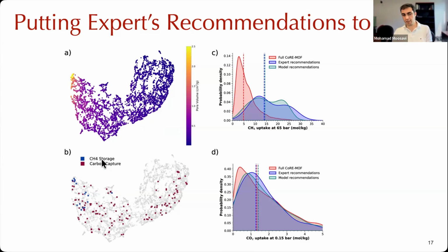One application in our case is methane storage. You see that the blue ones are mostly on this side. The other one is carbon capture. It's basically everywhere on the chemical space. Now we can look at the distribution of the properties that we have for these two applications. For methane storage, the recommendations from experts is actually very good. So this blue one shows the distribution of methane uptake at a certain pressure compared to the full database.